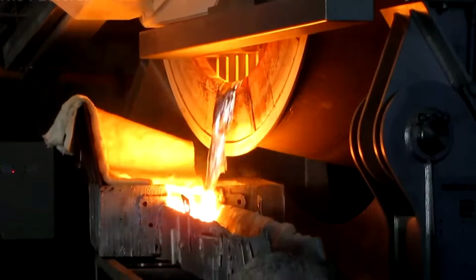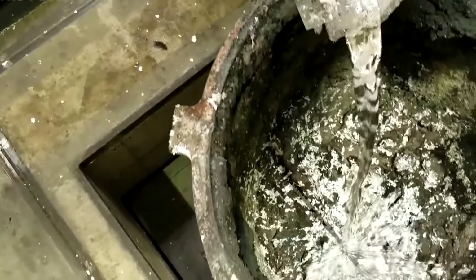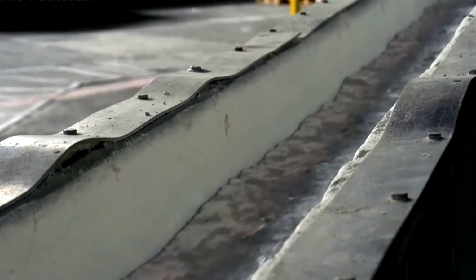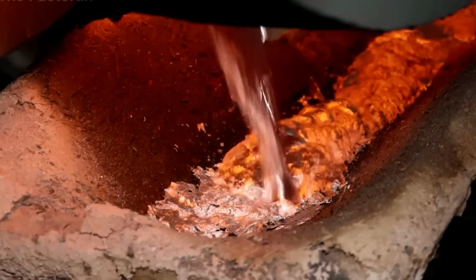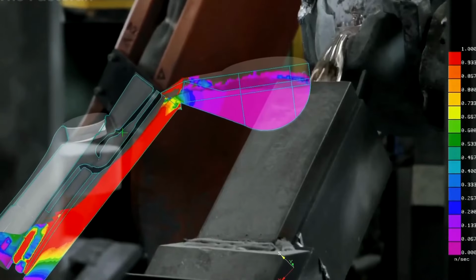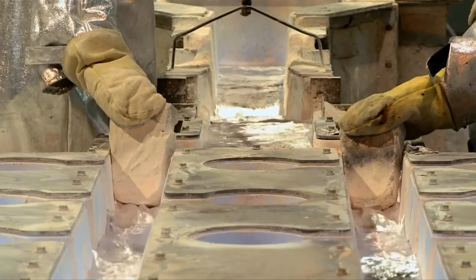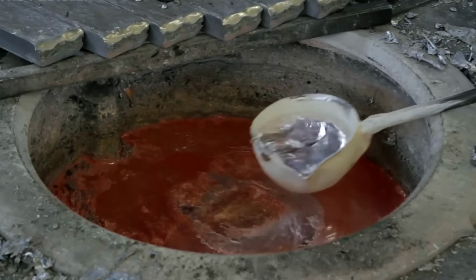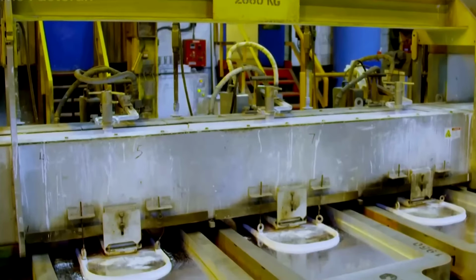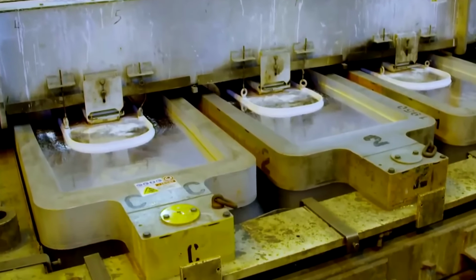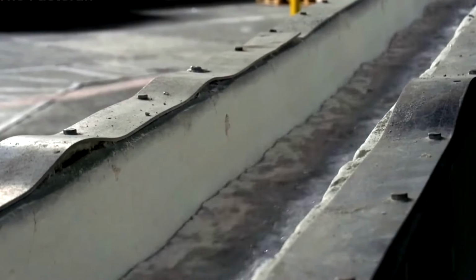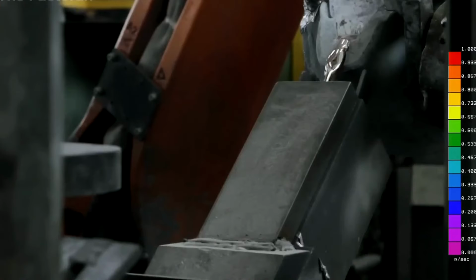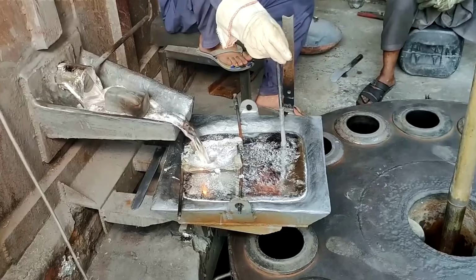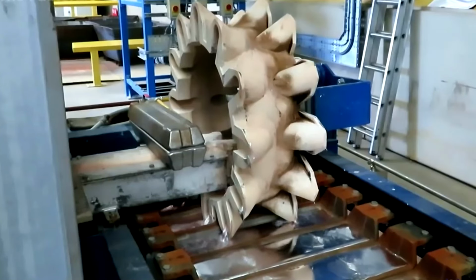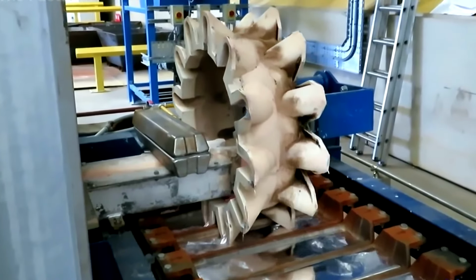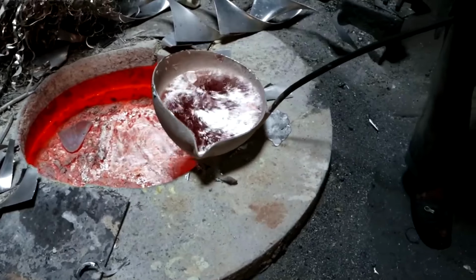Every detail, from the pouring speed and mold temperature to the intensity of the cooling, is precisely calibrated. A pour that is too rapid can trap gas pockets or introduce surface cracks, while a mold that is too cold risks uneven solidification, creating hidden structural flaws deep within the metal. Each parameter must be perfectly balanced, like guiding a powerful current through a narrow channel, as the slightest deviation can distort the entire product. In many modern facilities, this delicate process is fully automated, with sensors continuously monitoring pouring height, cooling rates, and surface temperatures. Yet in some semi-manual lines, the control still rests in human hands, a task demanding sharp instincts and split-second precision from skilled workers who command the flow.